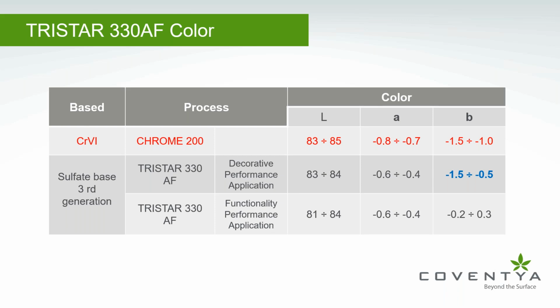Well, this table compares hexavalent and trivalent coordinates. As you can see, the value of L and the value of A are very similar. Regarding the B value, we notice that the decorative version is very similar to the hexavalent coordinate, with a very negative B value of minus 1.5. Even the functional version has a B value tending to the negative. In summary, both versions, but mostly the decorative one, can be mounted with hexavalent chromium items without noticing the difference.